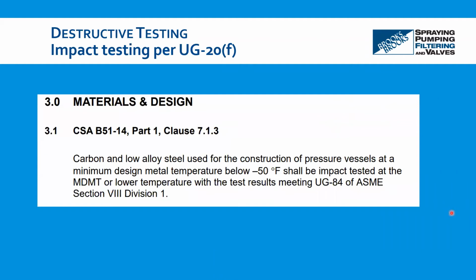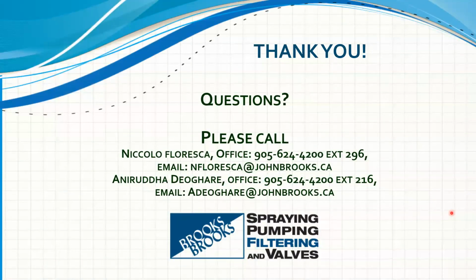Now, if the vessel were to be purposed for installation in Canada and, say, the minimum design metal temperature were to be less than -50 degrees Fahrenheit, we actually have no choice but to conduct impact testing. And with that, we open the table here for questions. Again, it should be noted that we covered quite a bit of content here, and we've only scratched the surface. This is the tip of the iceberg, so to speak.